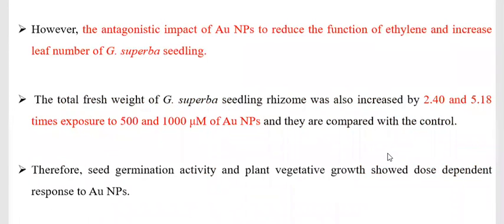Node elongation was also found to follow the same trend with 50 micromolar of nanoparticle. Node elongation of 4.5 was revealed, while control was 4.33 respectively. By contrast, the most significant effect on node elongation was observed at 100 micromolar of nanoparticle. The observed phenomena are attributed to the increased level of GA3 in response to shoot elongation.